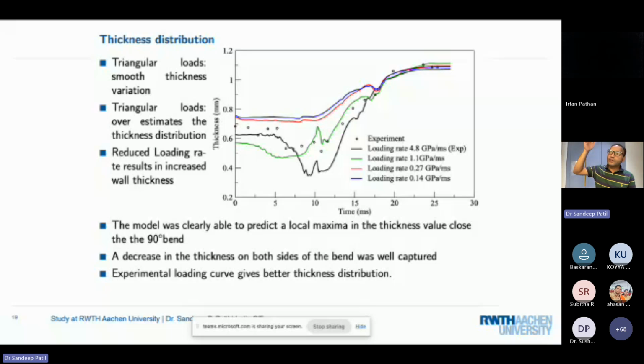And an important parameter we wanted to study, which many people have also studied, is the thickness distribution from the exterior edge to the center of the blank. What we did was cut the deformed sample and measure the thicknesses, and that's what we plotted with circles, which are the experiments. Then we carried out the simulation and checked the thickness distribution, and we found that the first impact, or plus peak load, is making a lot of deformation. You can see that the green and black curves are getting nicely close to the experimental data, especially the black one, which is pretty close.